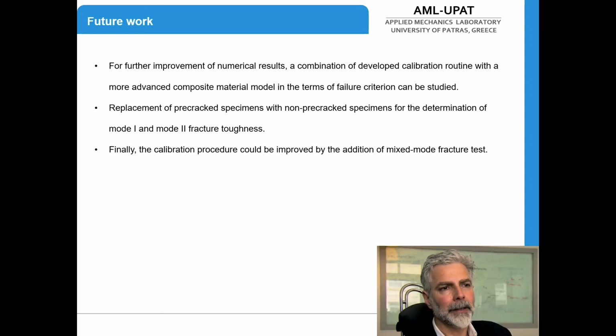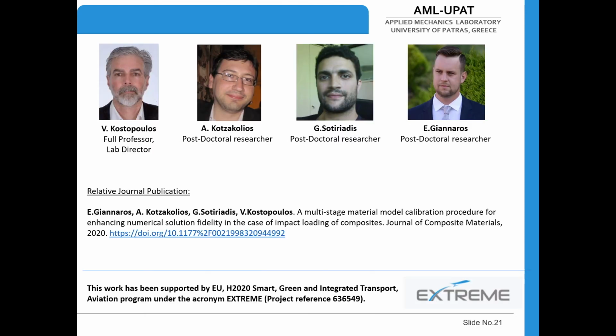It is clear that the proposed approach has many ways of improvement. First of all, someone has to try to see up to which level of energy this is valid. We have to check also the case of mixed mode and how we can consider this mode mixity in the results. And of course, we have to consider whether it is necessary to use pre-cracked or not pre-cracked samples in the case of Mode 2 experiments. But the most important point is that we have to very carefully see which is the level of use of this kind of approach. Thank you very much for your attention.